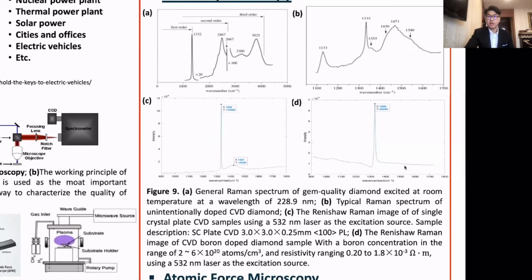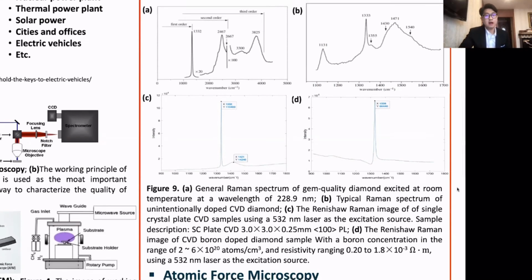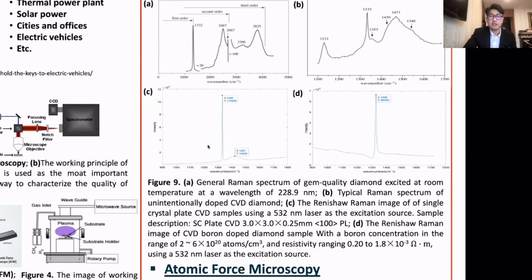The spectrum is dominated by the peak of 1332 inverse centimeter. And since the sample is heavily boron-doped, the peak has a Fano line shape, and combining that with some background fluorescence probably give rise to this type. Oh, by the way, both Figure C and Figure D are tested under the same condition with the 532 nanometer laser as the excitation source.